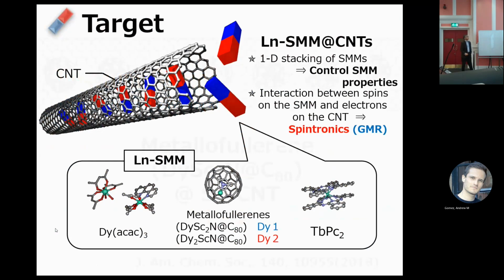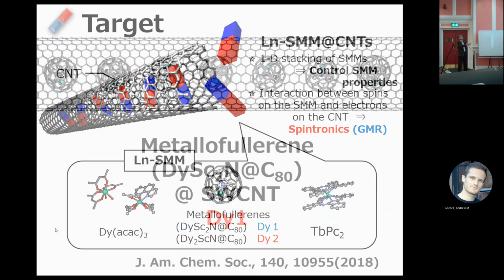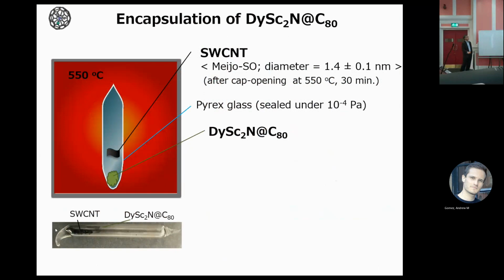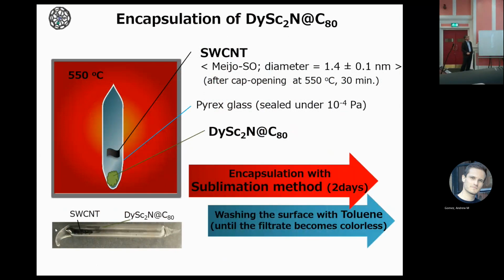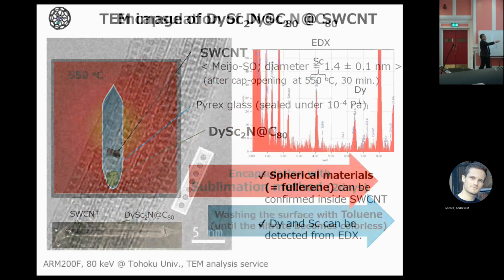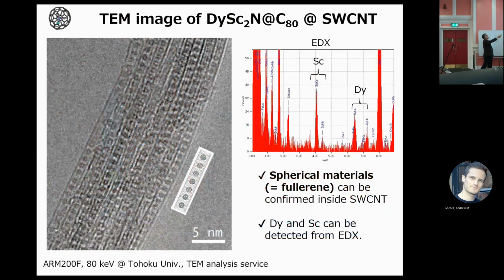We inserted. So this is a peapod. So very easy. High vacuum and high temperature for a few days and wash outside. So this is a TEM image. This is a peapod. You can see metallofullerene inserted. So in the EDX, deposition scanning, it is actually inserted.